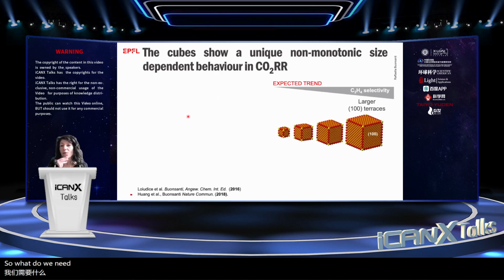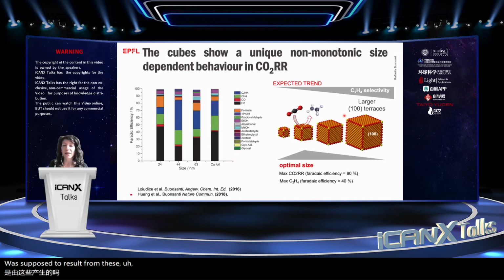So what we did was to then test these cubes for the electrochemical CO2 reduction. And what we were expecting at the time, based on the knowledge on single crystals, was that the larger and more extended the 100 facets were, the higher the Faraday efficiency for ethylene was supposed to be. Instead, this was not what we found. Here I'm reporting the Faraday efficiency versus the size of the particles. The Faraday efficiency is how many electrons are converted into certain products. And this black bar is the hydrogen, which is always hydrogen evolution, always competing with the CO2 reduction.